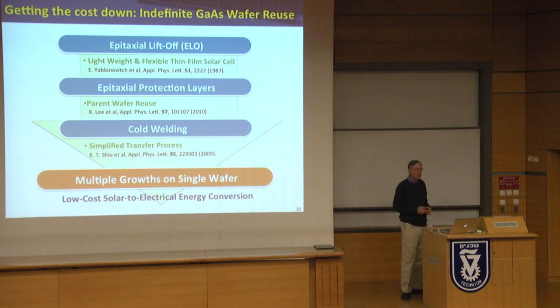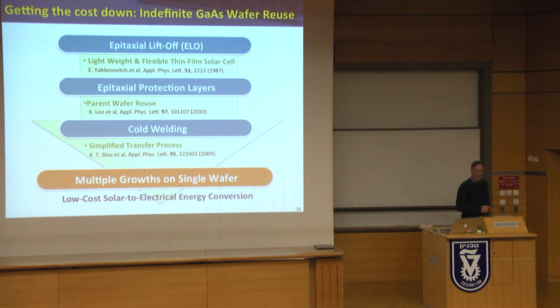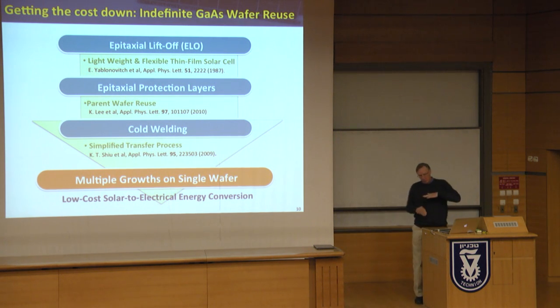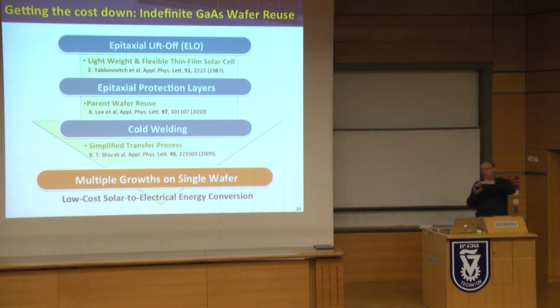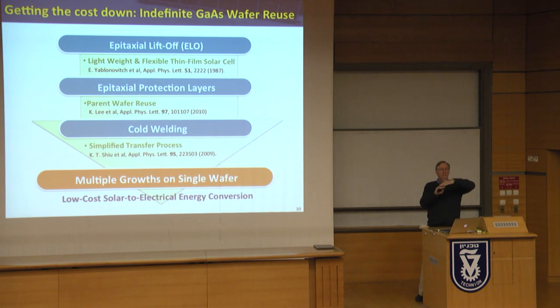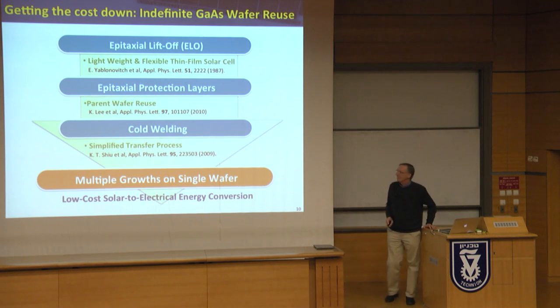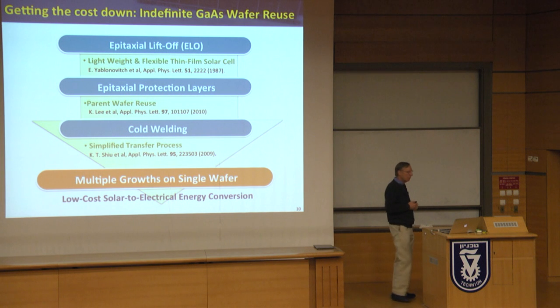Yablonovitch demonstrated solar cells by a process called epitaxial liftoff, where basically you grow your epitaxy on top of your wafer. You have some sacrificial layer. I'll show you this in a little bit more detail coming up. You etch out the sacrificial layer that peels off your epi. You glue it to a handle, then you transfer it to another substrate. That looked like it was really going to go far.